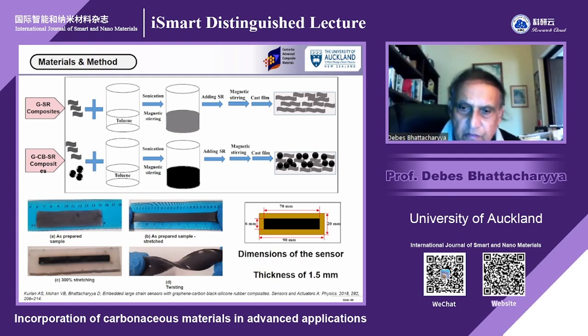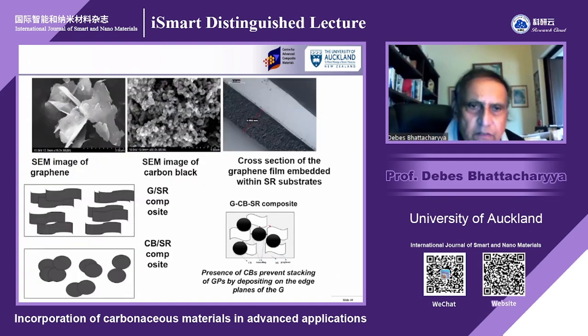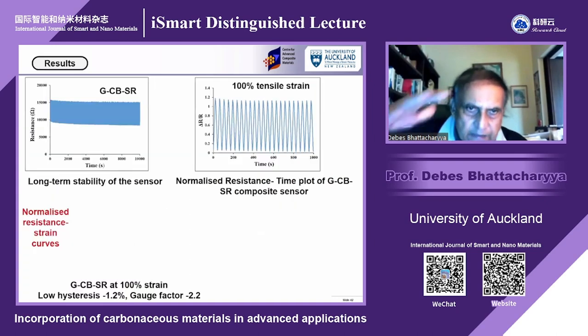We have published in Sensors and Actuators how this carbon black can help maintain the conductivity, helping your nanoplatelets get this kind of tunneling effect. You can see it even in microscopic pictures: those carbon black particles have infiltrated inside. This is the picture. It prevents stacking, so they won't touch each other. There will be something in between the two platelets, some kind of opening between the two, rather than very rigid contact.